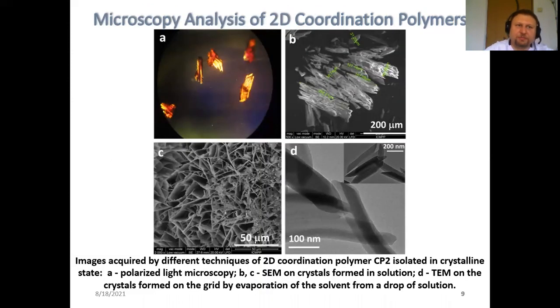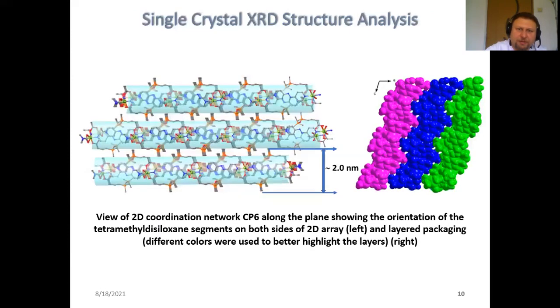The coordination polymers can be isolated as single crystals and can be analyzed by polarized light microscopy, by scanning electron microscopy, and transmission electron microscopy. The results from X-ray diffraction analysis show the orientation of the tetramethyldisiloxane segments on both sides of the two-dimensional array in the left image, and the layered packing of the polymers in the right image.